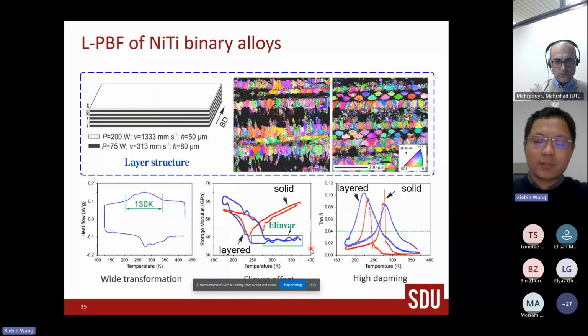For this layer structured material, the elastic modulus is almost constant with a change of temperature between 250 degrees and 370 degrees. And for the conventionally made nickel titanium alloys, the elastic modulus decreases with the decrease of temperature. And also it shows very high damping properties over a wide temperature range. The blue curves are for the layered material, and the red curves are for the wrought nickel titanium plates.